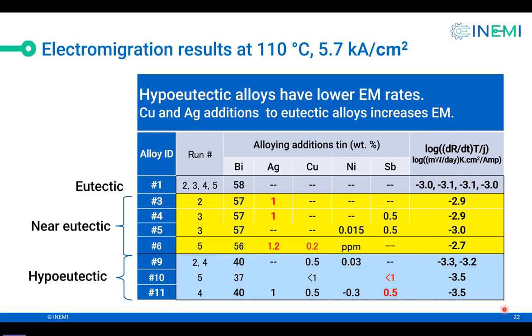Now the results are shown in the column on the right. I'm showing electromigration in terms of log of dR/dt times temperature divided by current density. So dR/dt is the rate of change of resistance, T is temperature, J is current density. Why am I showing results in this form? I'll explain that soon. But for the time being, assume that this is a good way to display electromigration results. Since it's a log and it's a minus value, the higher the minus value, the lower the electromigration rate. If you look at eutectic tin bismuth, which is alloy 1, it only has bismuth, no alloying elements. So the rate is about -3 to -3.1.